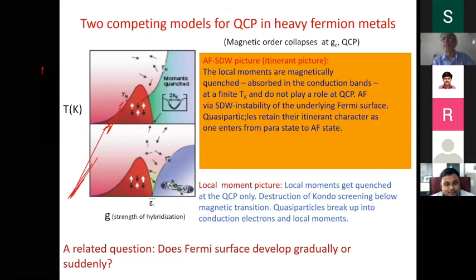There are theoretical attempts to understand this, because of the features of the Kondo effect. By that we mean there is a delocalization of the 4f electron. Instead of remaining completely localized, it becomes delocalized. It tries to become itinerant, which is another terminology for delocalization. So, put in simple words, in the region where you are supposed to see localization of the 4f electron, which should lead to magnetism, you also see a tendency for delocalization, if you look at the experimental features.